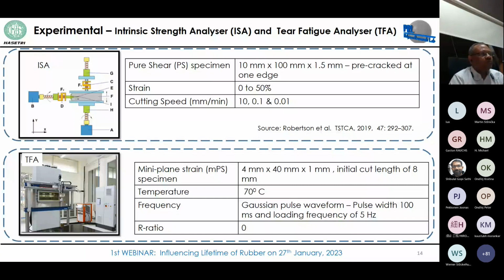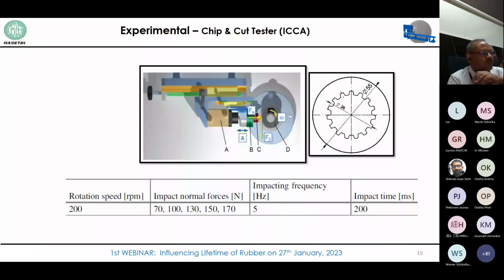The next experiment was done on the chip and cut tester from the ICCA instrument. This is again made by Coesfeld, and this is the type of rubber specimen used, having an outer diameter of 55 millimeter and 26 millimeter inner diameter, with rotation speed kept at about 200 RPM. We measured different normal forces, from 70 to 170. The impacting frequency was 5 hertz and impact time was 200 milliseconds. The output is, under those impact normal forces, the shear forces responsible for creating the cuts or chips, which are measured.